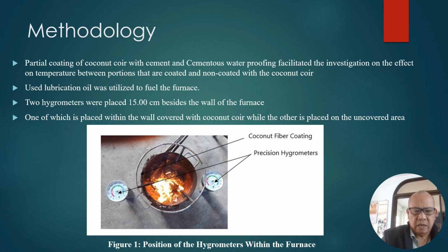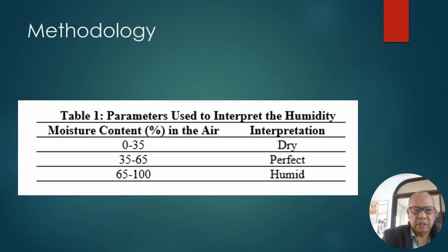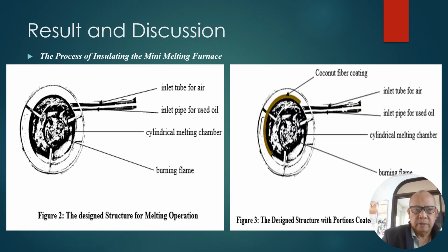In figure 1, you will see the position of the hygrometers within the furnace. To interpret the humidity readings on the hygrometers, if the moisture content is 0 to 35%, it is considered dry; 35 to 65%, it is perfect; 65 to 100% is humid. For the process of insulating the mini melting furnace, I present figure 2 and figure 3, where we will see the difference between the design structure for melting operation and when the structure was coated with coconut fiber.